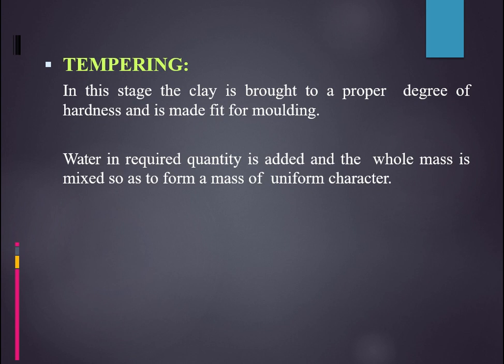Okay, and generally this will be carried out by storing the soil in a cool place, in layer form, each layer having about 30 centimeter thickness, and for not less than 36 hours. So the minimum duration of kneading required is 36 hours, and hence we ensure that after 36 hours we get a good homogeneity in the clay mass whatever we have taken, and hence it can be sent forward for the next process. And also if the amount of clay is huge, if it is in bulk, so one can't complete the tempering action in less than or equal to 36 hours, I mean 3 days.